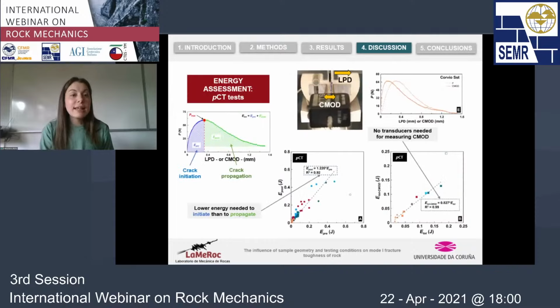Thanks to recording the complete load displacement curve, we could compute not only the area here, the energy needed to initiate the crack before the peak load, the pre-peak energy, but also the post-peak energy, that is the energy needed to propagate the crack. By plotting one magnitude against the other, we observed that in general, there was a lower energy needed to initiate the fracture than to propagate it.